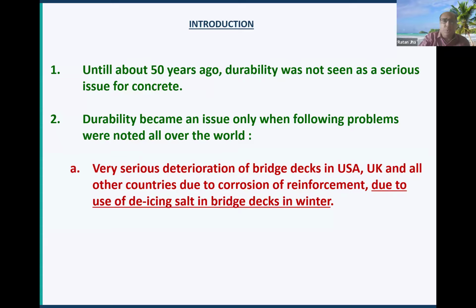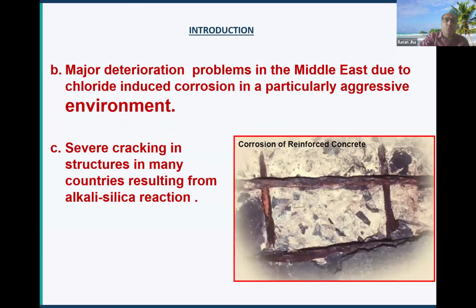But due to this process, de-icing salt, several cracks in bridge decks were found. Many cracks appeared, this type of crack. And as we know, the major deterioration problems in the Middle East were due to chloride-induced corrosion in a particularly aggressive environment. Severe cracking in structures in many countries resulted from alkali-silica reaction. So these are a few regions where construction engineers, project engineers, started thinking about durability as a main concern. They started giving more or equal emphasis to durability parameters along with the strength parameter as well.